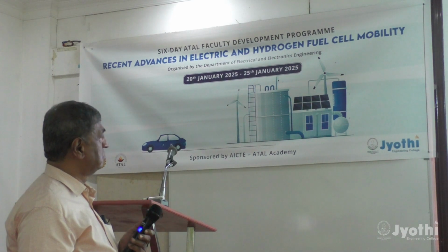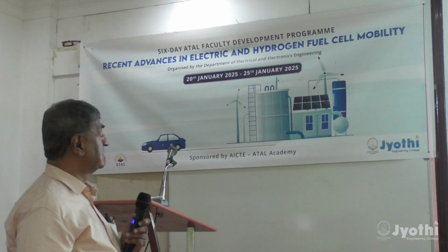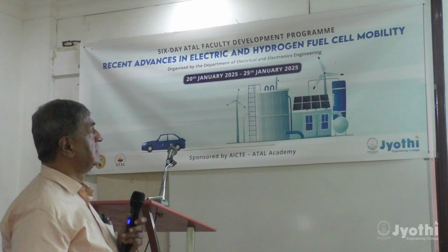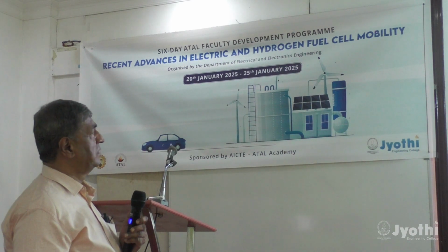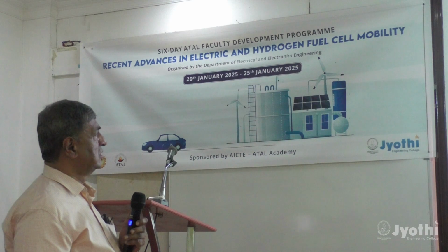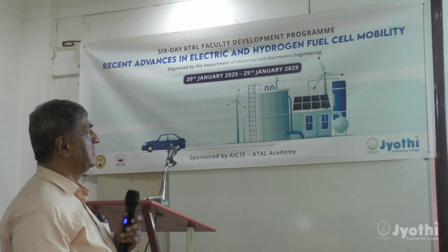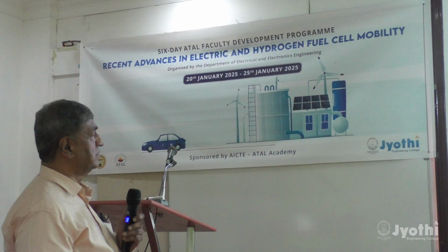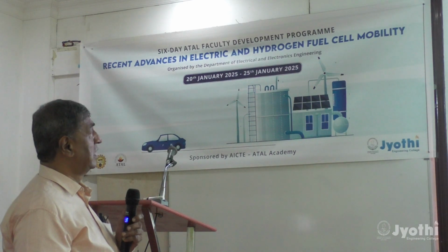So you may say that because platinum is not used, only nickel and ceria are used, so it's an inexpensive facile treatment based approach. Basically this heat treatment was doing annealing of the electrode deposit coating on the stainless steel substrate, and it boosts the activity towards HER.